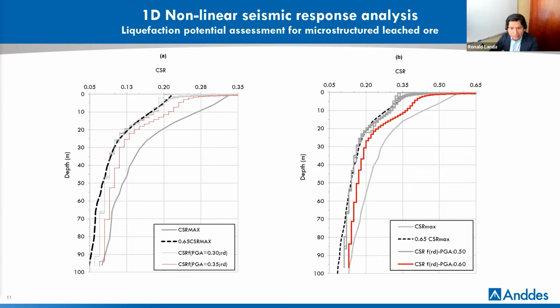These figures depict the calculated profiles of the maximum shear stress to vertical effective stress ratio obtained from this 1D analysis. It was conducted in terms of total stresses, considering that the soil seismic drained response is approximately equivalent to its undrained response before liquefaction triggering. It is intended to fit the PGA to the calculated soil seismic response. It's a package deal, because we need to pick a PGA and a shear mass participation factor, and fit them to the seismic response to obtain that maximum CSR.